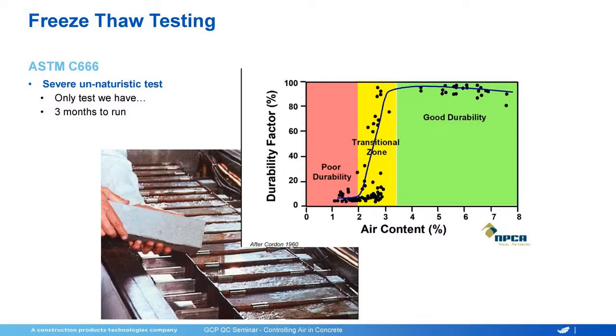However, with some very good concrete mixes and some very good air systems, we can see good passing or good durable concrete at 3%. We've seen some of that. Again, very low water cement ratio mixes with some very good 3% air can survive that. Okay. Don't see that often. Typically what we're looking for is, again, up in that 4+% with low water cement ratio as well.